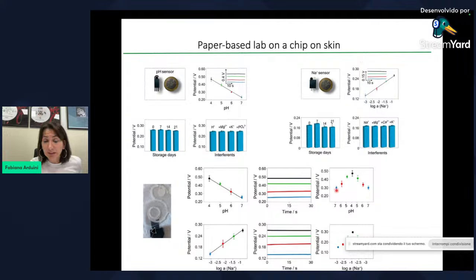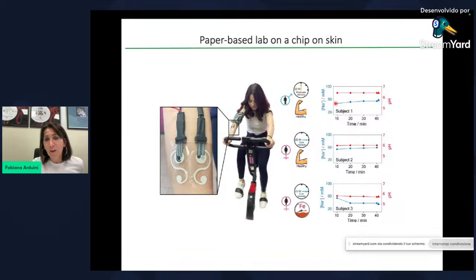And this is very important, that we studied the hysteresis, and we can see that starting from pH 7, moving to pH 4, and coming back to pH 7, you obtain the same results without memory effect. This demonstrates that it's possible to detect in continuous, without memory effect, the pH and also the sodium concentration. This is the continuous analysis, and we test the sample only at the end by the reference method, obtaining a good agreement.